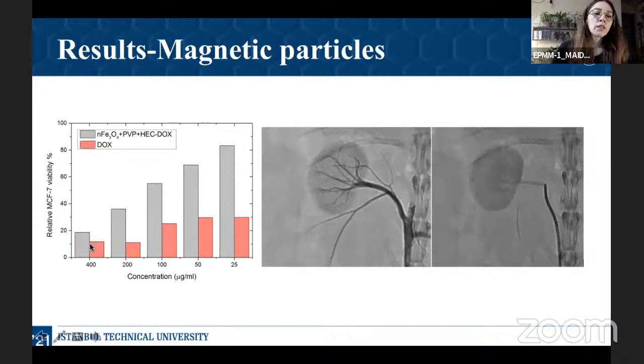Later on, we tested our particles in cancer cell lines, MCF7, which is a human breast cancer cell line. Here we can see that our magnetic particles were as effective as pure DOX, which is represented in orange bars here, at the highest concentration. But as the concentration lowered, the gap between pure DOX and the particles increased, which indicates that we should use the highest concentration when using it for chemoembolization applications.